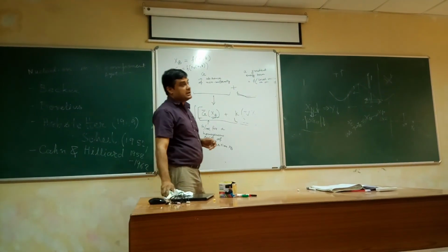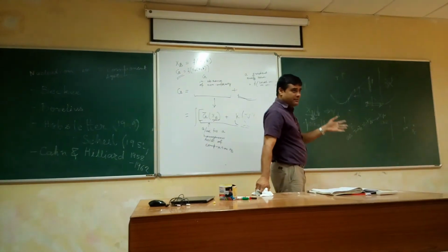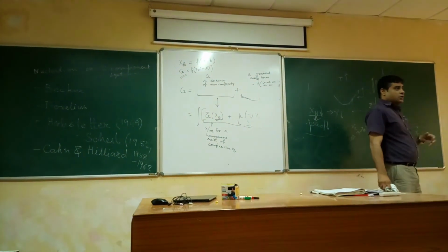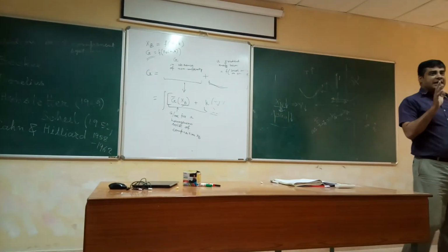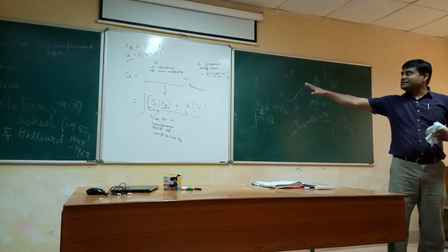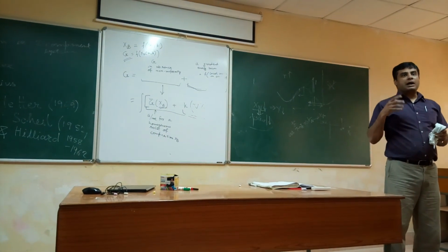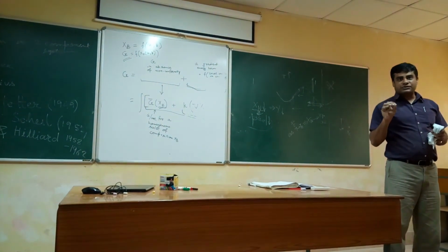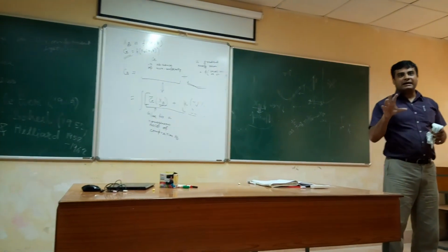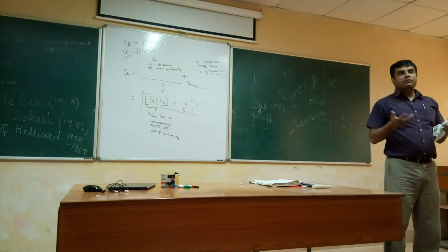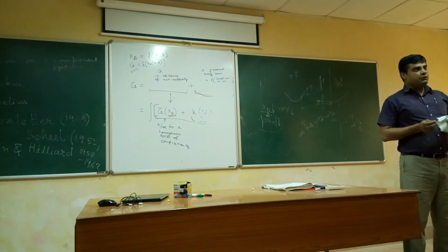So diffusion coefficients can be written in terms of chemical potential. So you can write both kinetic equation as well as the thermodynamics together to come up with how a microstructure evolves, starting from nucleation and in the growth stage, how any new precipitate forms.